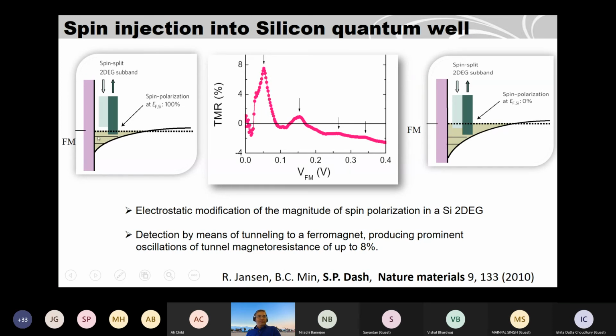When you hit these bands, you should see a maximum of the tunnel polarization. And that's what we see here. When we tune the electric field to go to these states, we see this maximum in the magnetoresistance.